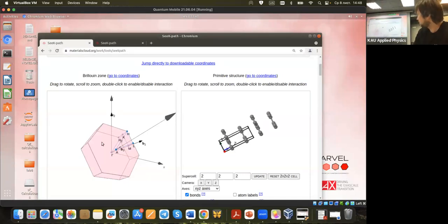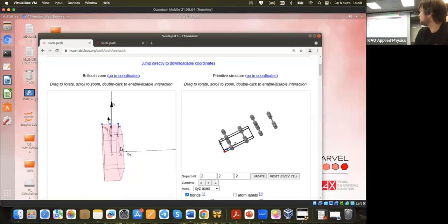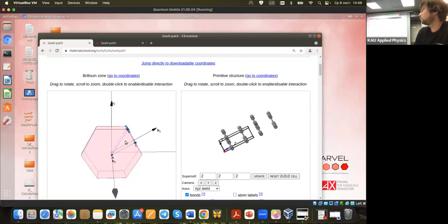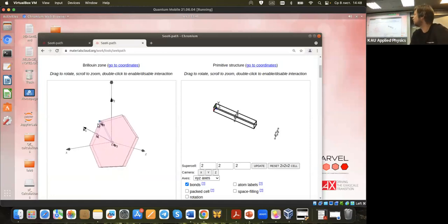That means that in reciprocal space, this vector should be 2.7 times bigger than this. And we see this is not as huge as this direction. That's why we need a lower number of k-points to calculate the energy in this direction. Almost 2 times, like 2.7. I took 2 times. But for graphene, I need only 1 k-point because I don't want to go bulk. I just want to stay in 2D.